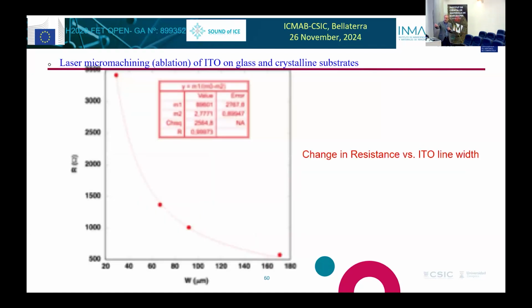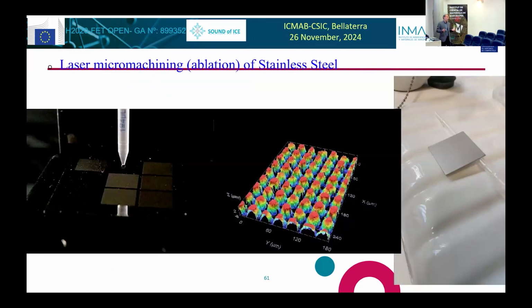And you can engineer, depending on how wide you make this, the resistance of this. So this is very nice because you can engineer a circuit with a specific resistance, which is ideal for what you want to make. You can also do something else. You can change the water behavior of the surface, change the water wetting angle, and you can do that by combining a microstructure with a nanostructure.